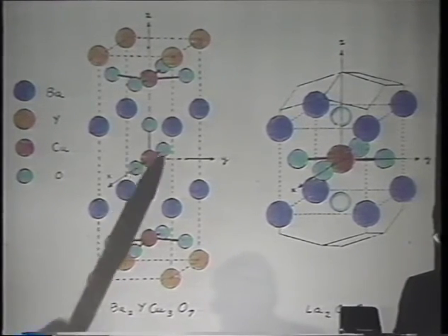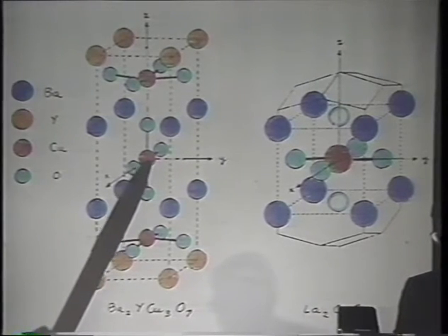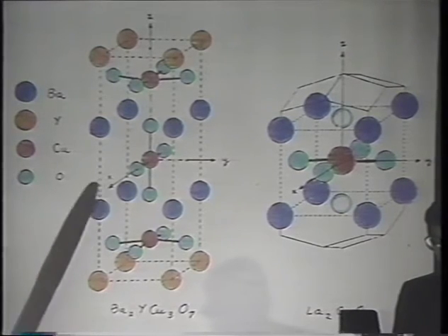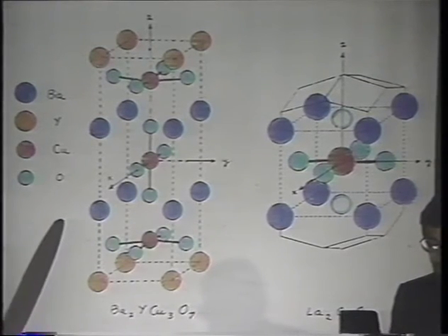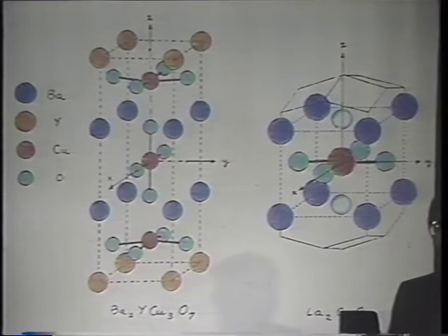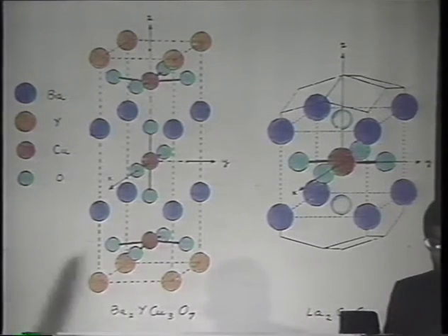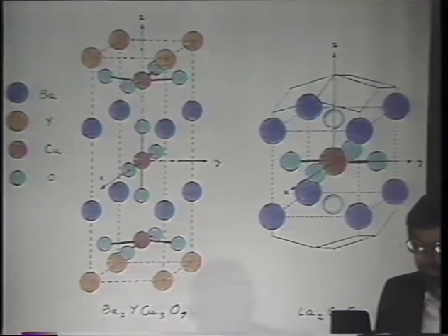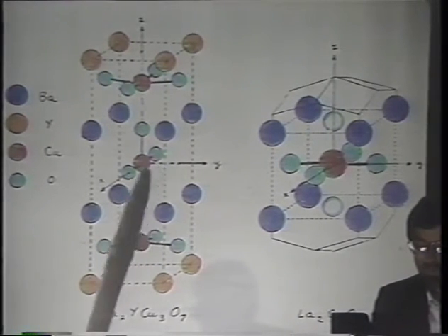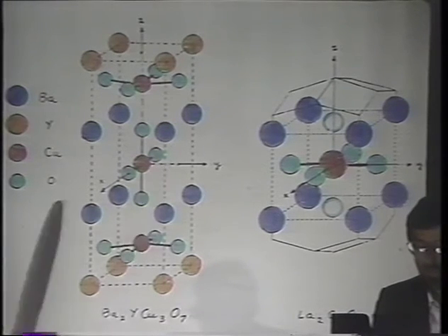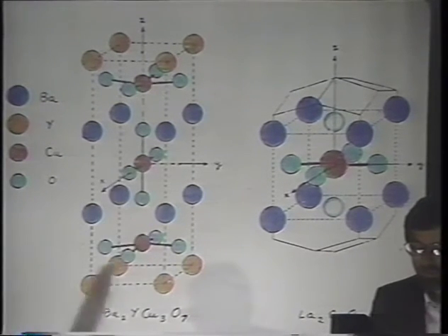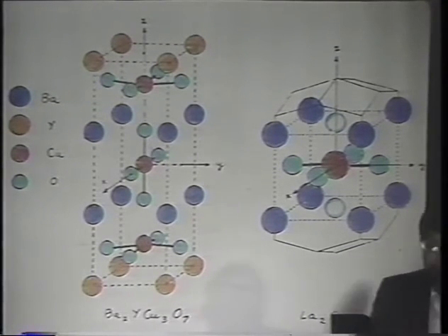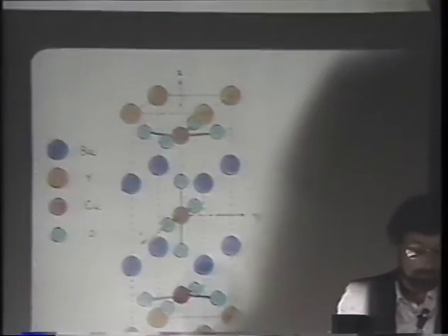This one-dimensional chain is shown here, a copper atom, which again is fourfold coordinated, so it is very happy, but it is connected only in the x direction. And this is due to the fact that the oxygen vacancies are sitting in this copper plane. What Len Mattheiss and Don Hamann have assumed here is that they order, and therefore you have a one-dimensional conducting chain combined with two-dimensional sheets over here. And as we heard before, if one sheet is good, more may be better.